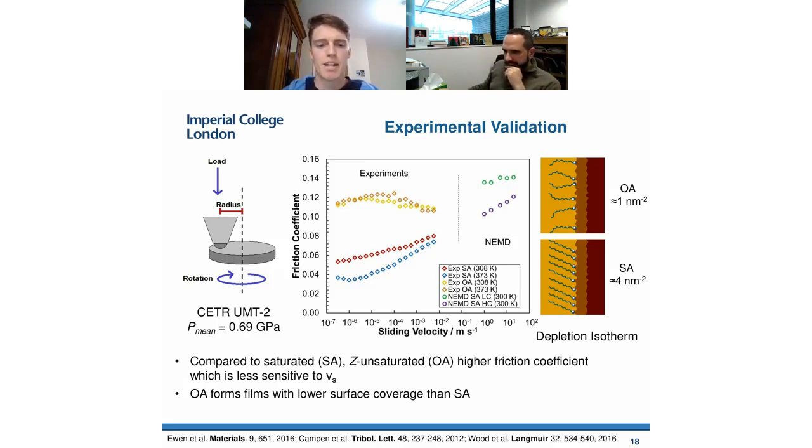which is of the order of nanoseconds and not very long at all, you've got to run quite fast to get basically a converged friction coefficient in the time that you've got. So that's commonly known with NEMD simulations. But what's nice is that because you can apply a very efficient thermostat to the walls in this case, you can suck all of the frictional heating that you would get experimentally at these speeds out of the system. So you're basically still in an isothermal case. So it's quite good to compare directly to experiments.